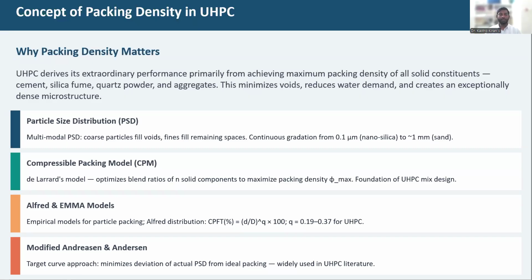So most of the people, how we check this packing density is we'll check the packing density with only the cement, silica fume, and any other materials that are used as supplementary cementitious materials. But in general, whenever we are testing the packing density of UHPC, the utmost preference has to be given to all the materials that we are using in the preparation of UHPC. So for all the materials combined together, it is important to measure the packing density.